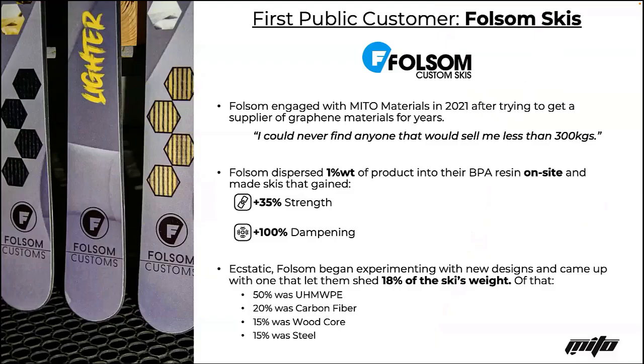So for instance, our first public customer is Folsom Custom Skis. Last year, they were trialing our product, and what they found is that with 1%, so 10 grams for the whole set of skis, they were able to increase strength by 35% and damping properties anywhere between 100 and 200%, depending on the fiber. This got them really excited because they could never find any graphene supplier that would sell them less than 300 kilos of the stuff. And even then, it was nanomaterials. He didn't want to handle it, and so he just put it on the back burner.